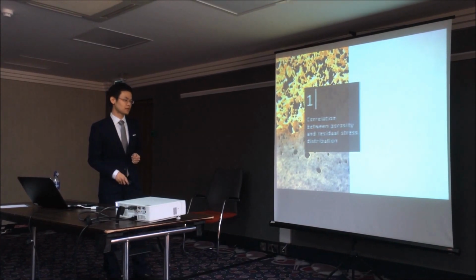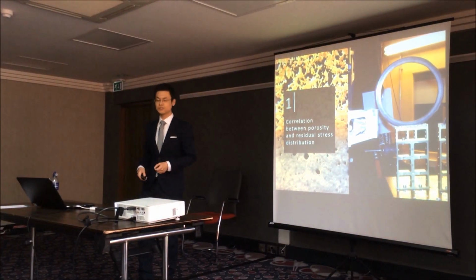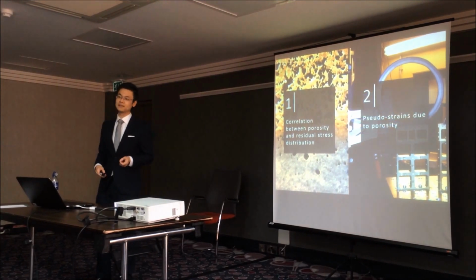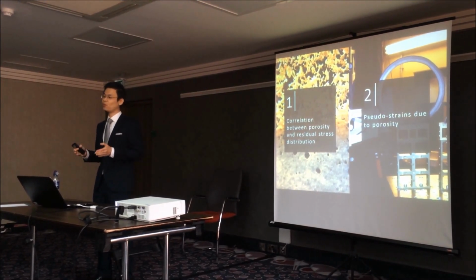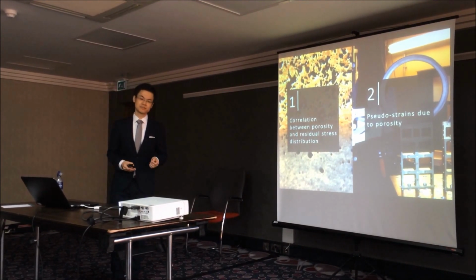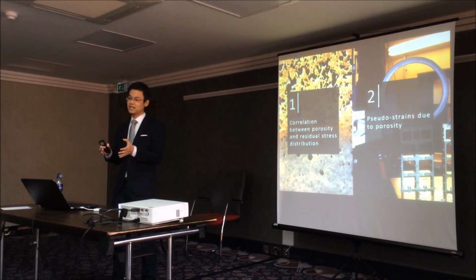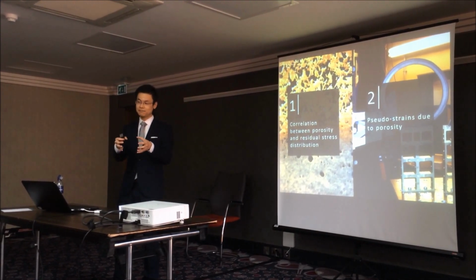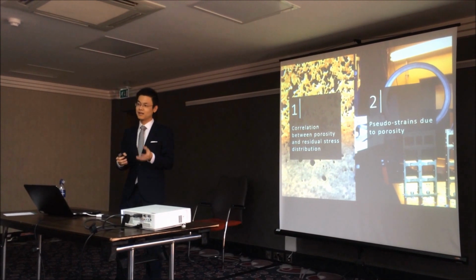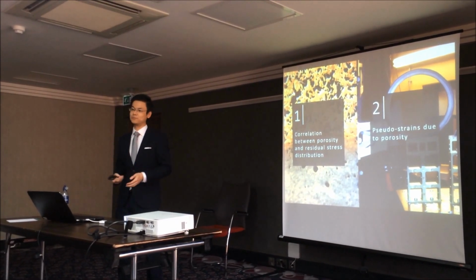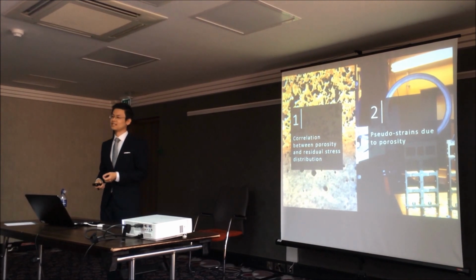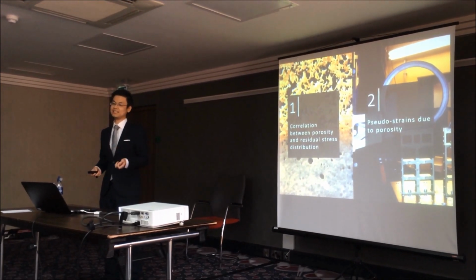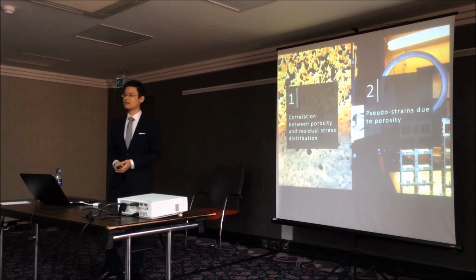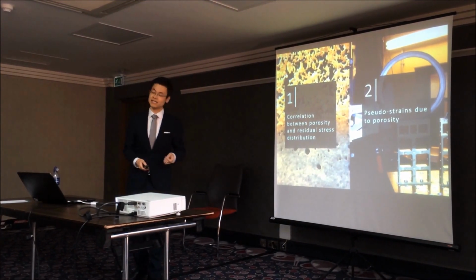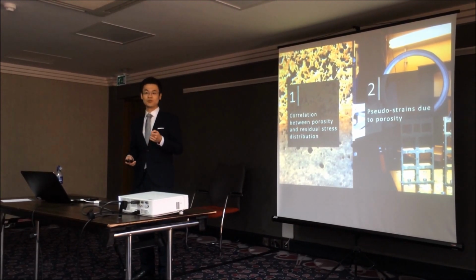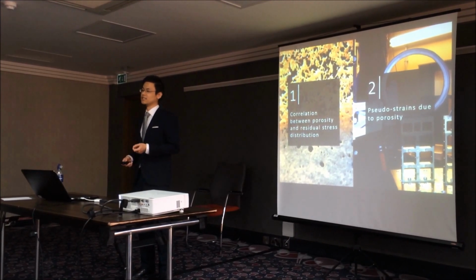Point number 2. Pseudo-strains caused by incomplete filling of the gauge volume in a sample has been widely discussed and accepted. But porosity, in other words, absence of material in tiny parcels within a component, can also lead to incomplete filling of the gauge volume. And to the best of our knowledge, this has not been widely or explicitly discussed, especially for sprayed steel. And in our case, we considered porosity-induced pseudostrain in our work using our sprayed steel.